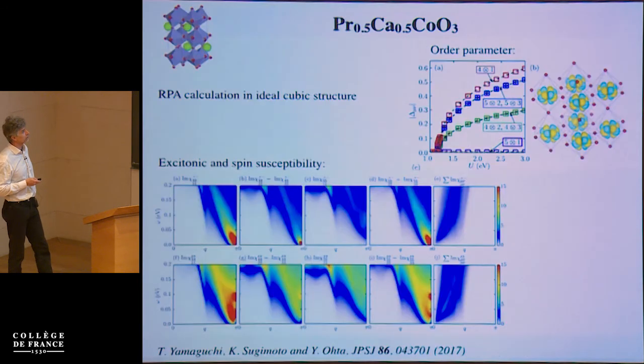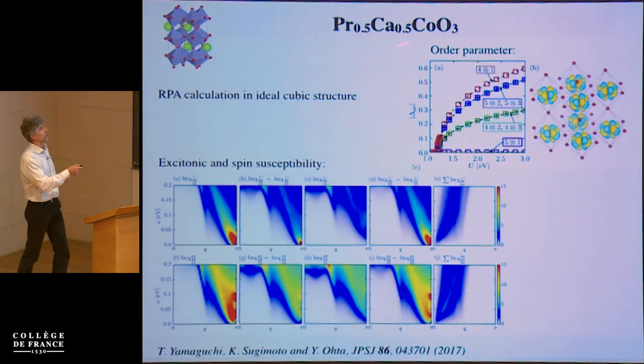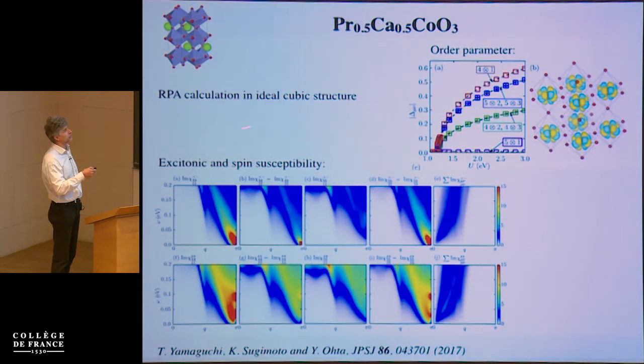There were also studies by other groups who used RPA, and they also observed this excitonic condensation, and they were able to identify the order parameter and calculate the dispersions in the ordered phase.